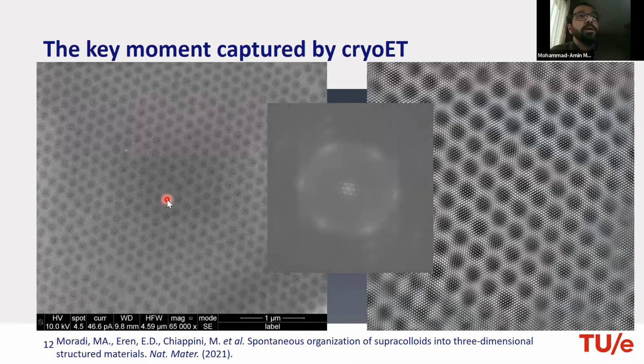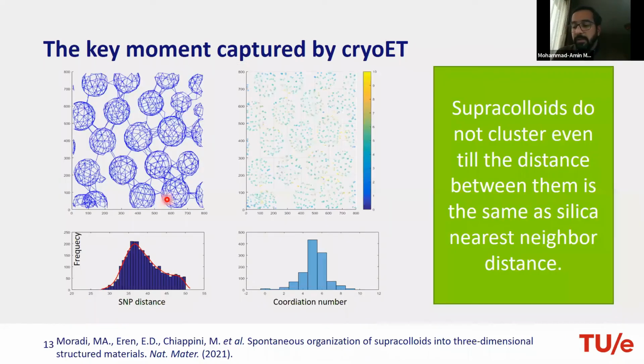And when we look into the analysis of the particles of this sample, it was very interesting to see that the silica particles sitting on one supracolloid particle are sometimes as close to the silica particles of the other supracolloid. So the material has gone this concentrated, but still no rearrangement of the silica particles happened. Which means that we sort of confine the replacement of the particles that happens at the final drying moments in a very narrow region where they cannot actually escape and make phase separation.